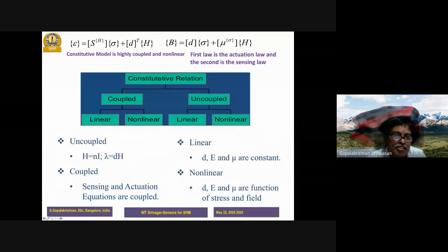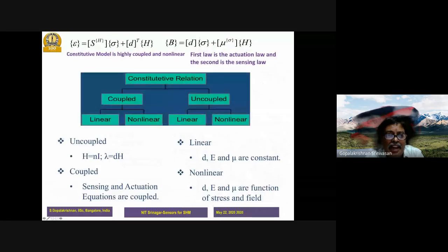If you look at the constitutive model, the strain is related to stress and also to the magnetic field. So D transpose H is called the Maxwell stress. This is coming from Maxwell's equation. This is the elasticity equation. The strain is related to stress as well as magnetic field, and the magnetic flux is related to mechanical stress and magnetic field through permeability. Here the compliance, the material property, is measured at constant magnetic field. And the magnetic flux is related to this one, with the permeability measured at constant stress.